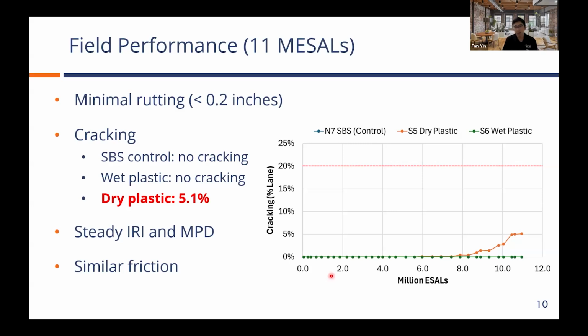But if you look at the cracking side, this is where we saw some very interesting findings. The wet plastic and SBS control sections have performed perfectly with no cracking. But the dry plastic section, as you can see here, started to show some cracking initiation somewhere between 7 to 8 million ESALs. And obviously the cracking has started propagating over time. At this point, we are at 5.1% cracking in terms of length and area on the test track. It will be interesting to see how long it's going to take for the cracking to develop to the point where we feel we have to take it out and call it the failure of the experiment. So overall, even though it's still early, this field performance shows a very consistent trend compared to what we saw in the lab.